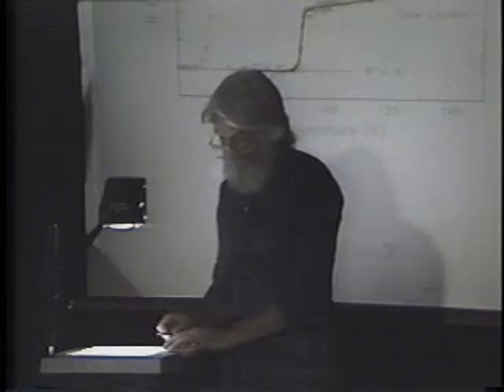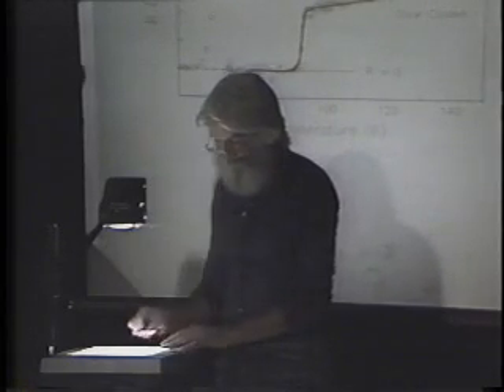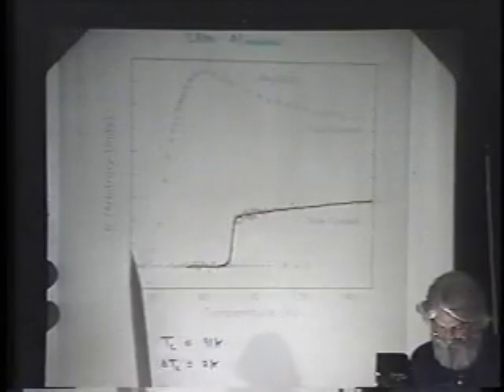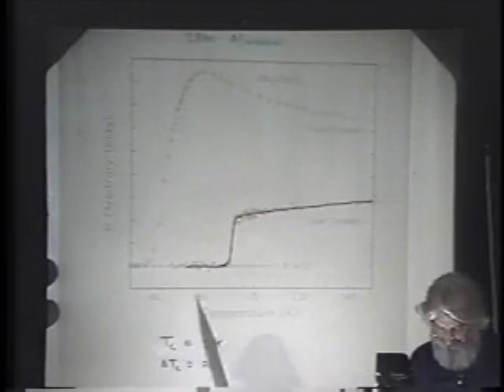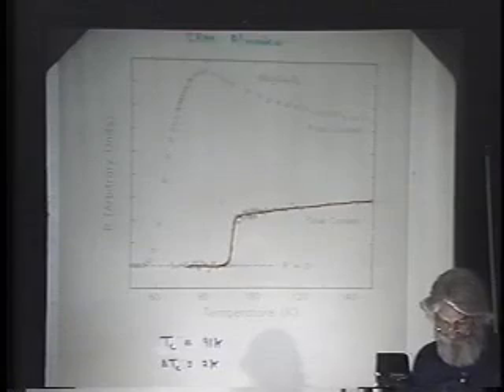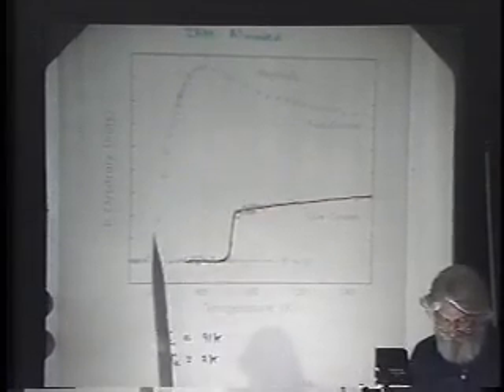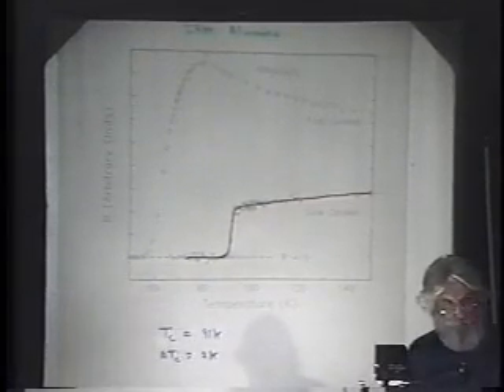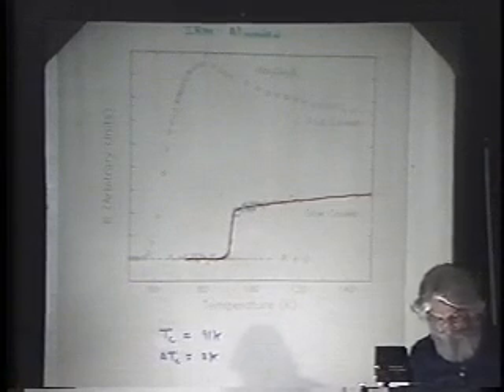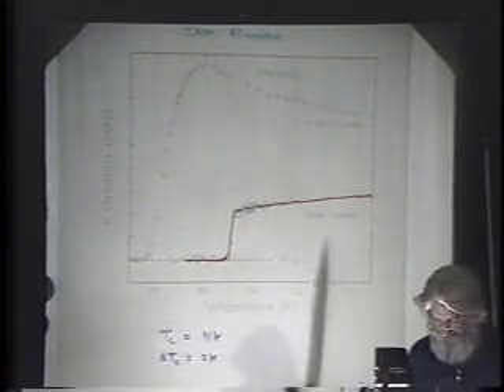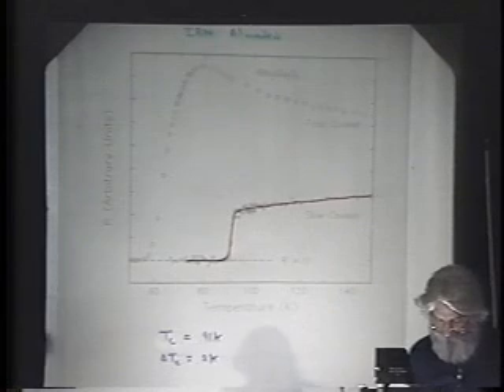Okay, just to show that we do superconductivity, here's a foil where, I don't know how well it shows, all right. Same sample, but annealed at different rates out of the furnace. This is fast cooling out of the furnace. This is slow cooled out of the furnace. You get two entirely different responses. Very percolative superconductivity for the fast annealed sample. Obviously, you're not getting oxygen equilibration. Slow cooled, it's very, very narrow.